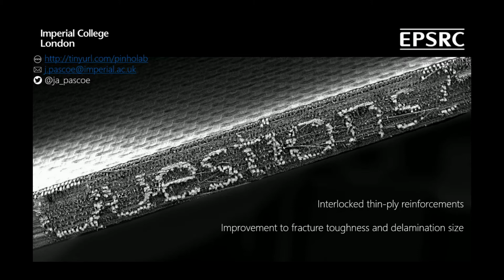Traditionally, researchers have sought to improve compression after impact strength by improving the interlaminar fracture toughness, for example with interleaves or translaminar reinforcements. Our results suggest that to obtain further improvements to compression after impact strength, especially at higher impact energies, we should instead focus on preventing or ameliorating fiber damage. We believe that we have only started unlocking the potential of ply-level and interfacial structures and are continuing to develop exciting new concepts in this area.